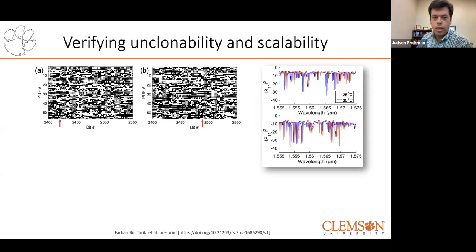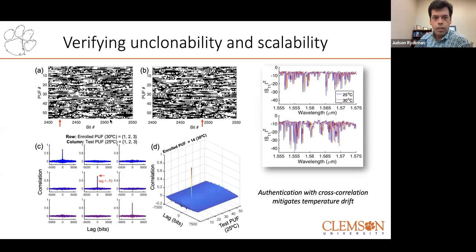It means that we can use a cross correlation to authenticate any two keys. So if we measure PUF number 1, it should authenticate with itself, and we see it's highly correlated to itself, despite the fact that the temperature has changed, but it does not correlate with any other device. And so we see this PUF 2 correlates with itself, but not any other.